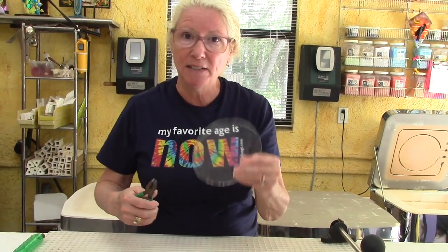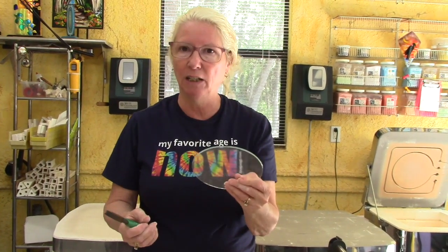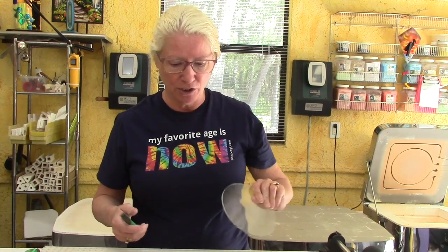So what we've learned so far: clear glass is the best thing to use because it's least expensive — you can go through it quickly. We learned our circle was a little larger; we measured the mold originally with a soft tape measure but concluded that was a little too big, so we made it a little smaller. We've concluded that 1200 degrees is too low and 1265 is too hot. We've learned a lot of information just from firing this kiln three times with plain clear glass.